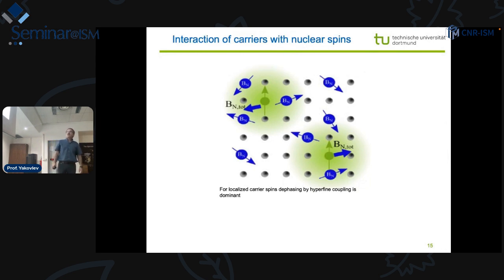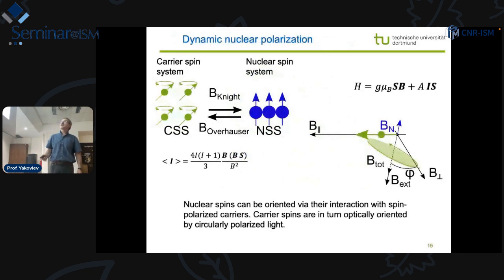Next thing, except for the electron spin systems, we also have nuclear ones. So these are the spins of the nuclei, which are sitting here. And the carrier, which is localized, interacts with a few nuclear spins, from 5 to 20 or 200. And these interactions have an effect on the spin polarization. We have a carrier spin system and we have a nuclear spin system. If we spin-polarize carriers by light, these carriers can transfer their spin to the nuclear spin system, and the nuclear spin system becomes polarized. But if the nuclear spin system is polarized, it can act back with its polarization on the carrier spin system.